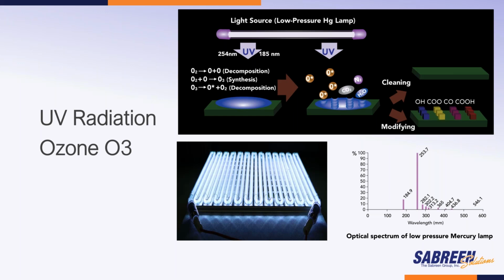Often neglected is UV radiation, which produces ozone. And we've got two primary wavelengths. One is the 185 nanometer UV light, which generally decomposes oxygen molecules and synthesizes ozone, O3, while the 254 nanometer UV decomposes ozone and produces high energy oxygen, which certainly helps to functionalize the surface. The surface will be cleaned from many organic contaminants and becomes hydrophilic.